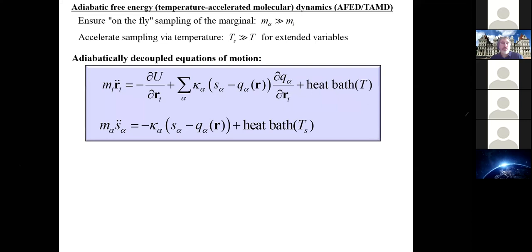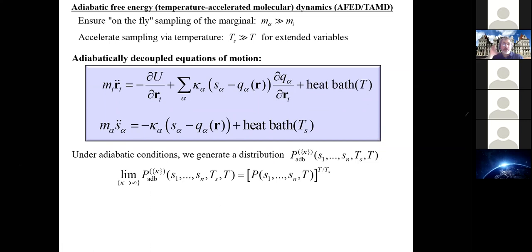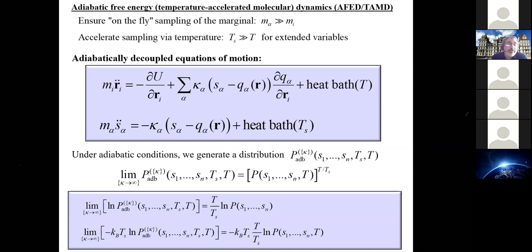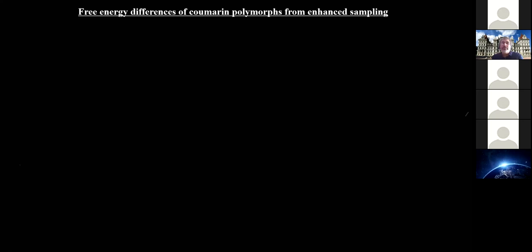What you can prove is that with these two temperatures, T for the physical variables and TS for the S's, you can generate a distribution called the adiabatic marginal, which is the true marginal raised to a power of the temperature ratio, T over TS. If I take the log of both sides, the log lets me bring down the T over TS factor, you multiply by kTS on both sides, the TS's cancel, and you get the free energy at the temperature that you want.